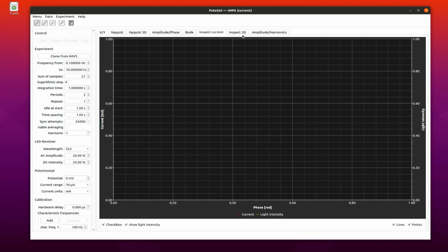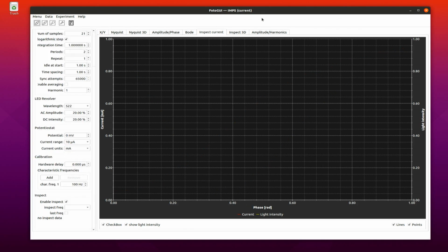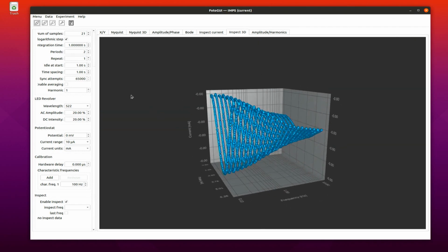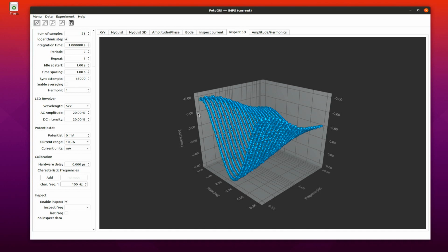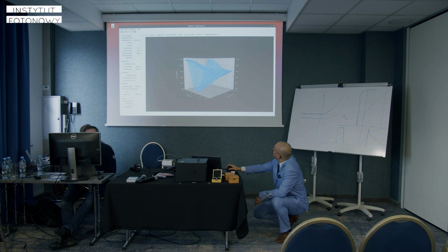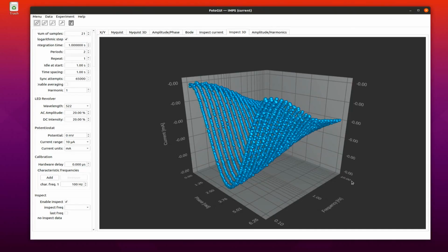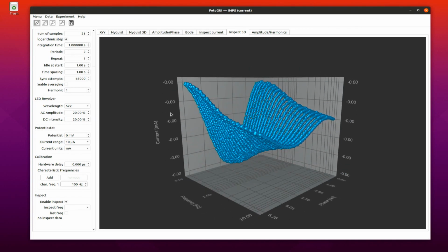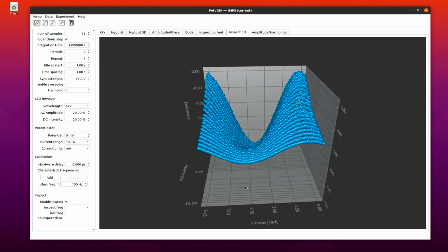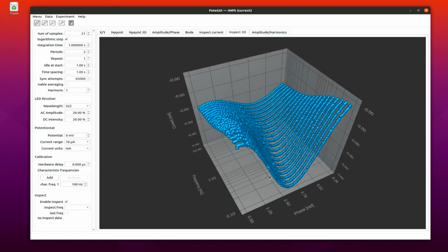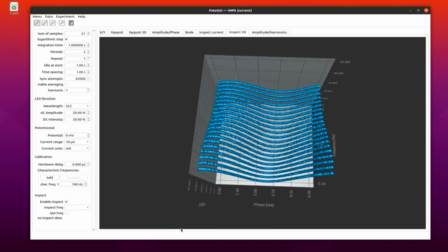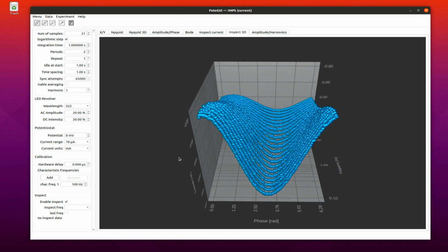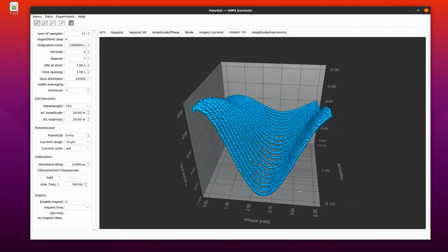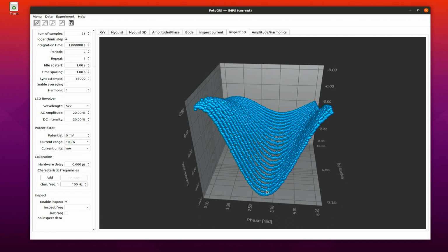And here you can see all the results. If we start from lower frequencies on this axis and go to the higher frequencies, we can observe that this curve flattens. And you can observe the phase shift. This is a delay between our sample response and the incident light.